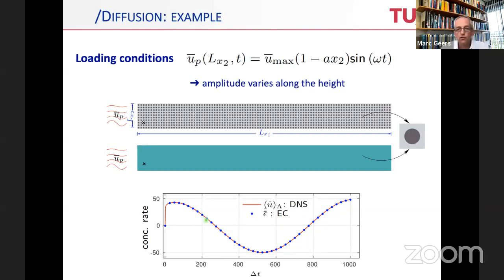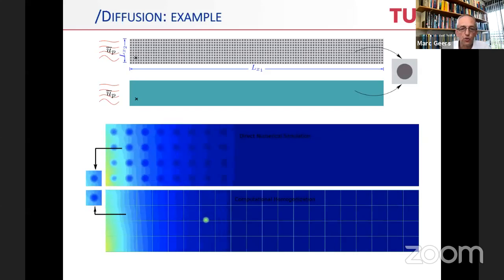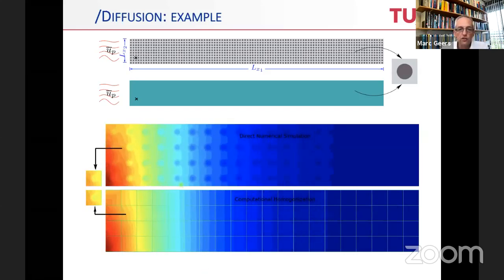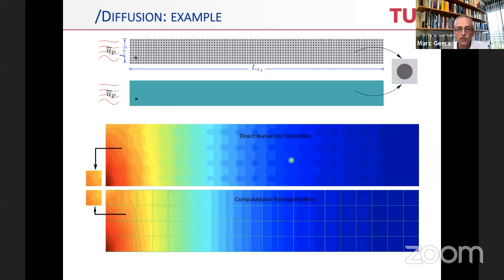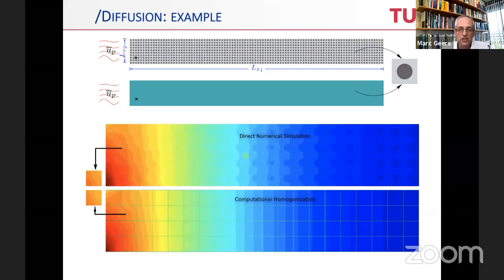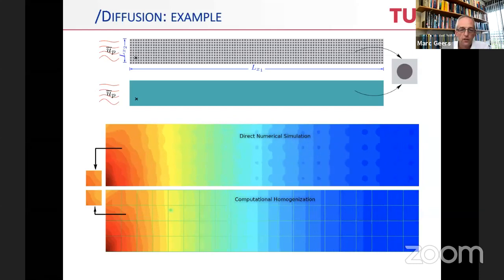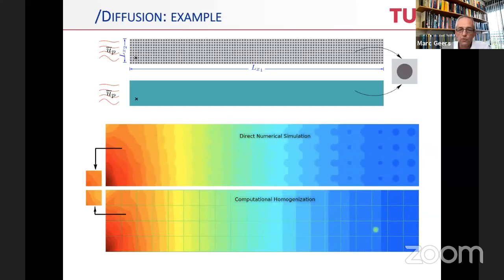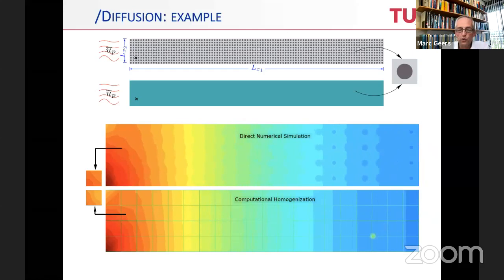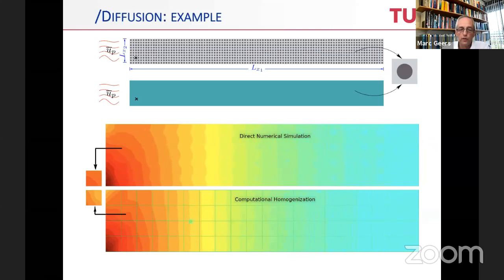You can also look into a movie. So I'm not sure whether this will pass well, but if it does, then you will recognize that the top simulation is the direct numerical simulation, because you can still see the inclusions if you watch well. The bottom simulation is the computational homogenization solution, where you don't see the inclusions anymore, but the fields that actually come out are very well comparable. You can also see that the slow inclusions have a clear influence on the whole propagation. So it has a marked contribution on the overall continuum, which is well captured by the homogenization scheme.